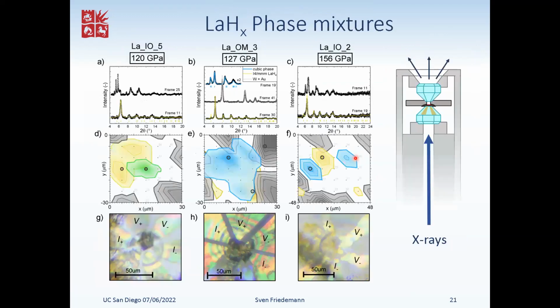We've then looked at it with X-rays and it becomes messy. We can see X-ray patterns that are consistent with lanthanum H4 in some parts of the sample, and then X-ray patterns which are consistent with some cubic structure in other parts of the sample. And then the question arises, which one of these is what you're measuring in resistance measurements? Because X-ray diffraction has a detection limit, and you could still have some filaments running through the various phases, and it becomes tricky to disentangle.